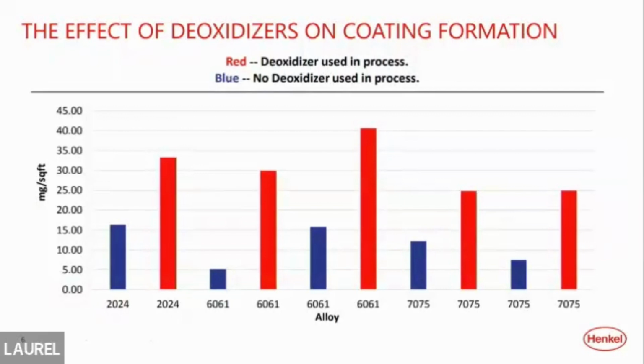So the use of deoxidizers for coating formation, regardless of the alloy. So we have 2000 series, 6000 series, 7000 series alloys. The blue is no deoxidizer, red is deoxidizer. And on the left is coating weights. So as you can see, if you don't use a deoxidizer, you pretty predictably get at least half of what you would get with deoxidation.